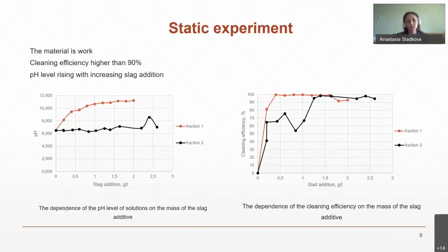And to study the possibility of removing metal cations from water, experiments were carried out under static conditions. The line graph on the left shows the changes in the pH level depending on the mass of the slag additive, and the line graph on the right shows the change in the efficiency of cleaning solutions depending on the slag additive. As can be seen from the graph, the efficiency of cleaning solution from the metal cations is up to 99%. The efficiency of cleaning solution with slag fraction 2 increases unevenly due to the larger particle size, and as a result, the interaction with the